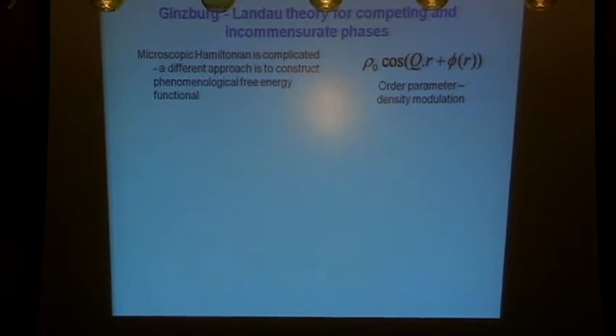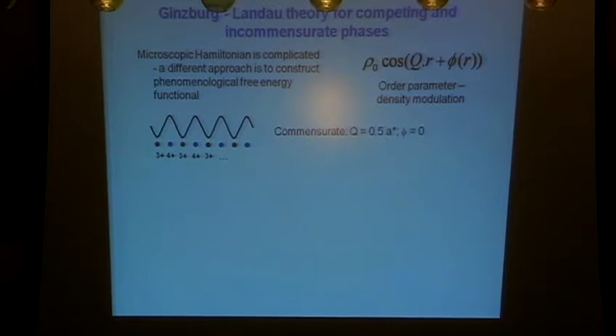And the idea of this phase, of course, is that the phase of the wave is associated with what the origin is. But if I allow the phase to be modulated as a function of space, then I can shrink or stretch the wave to locally change its periodicity. Well, why would I want to do that? If I want to model something which goes 3 plus, 4 plus, 3 plus, 4 plus, what I would do is choose a wave vector which is exactly one half of the reciprocal lattice vector, and a phase of, say, 0 to line up with these. So I get this red, blue with min-max.